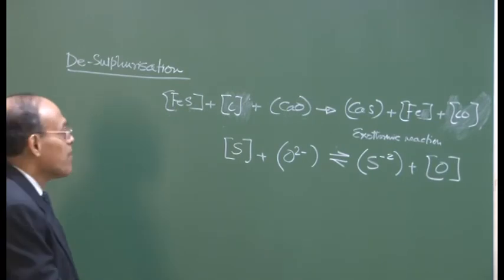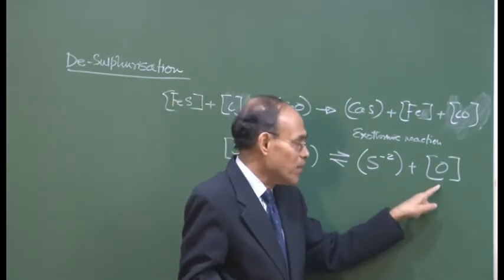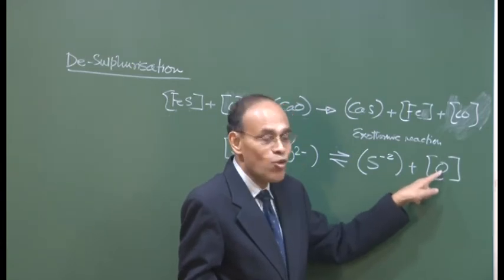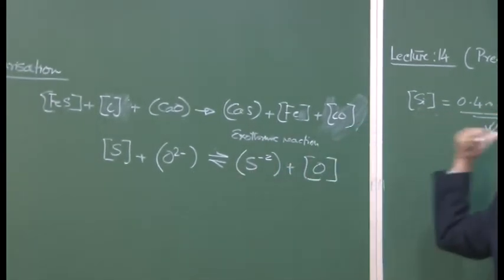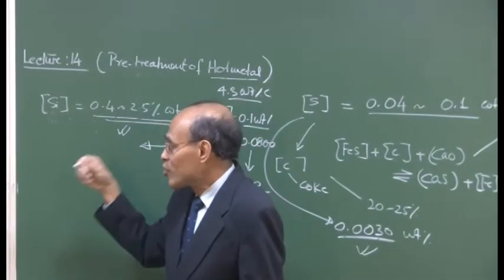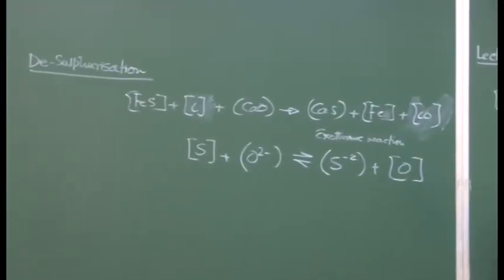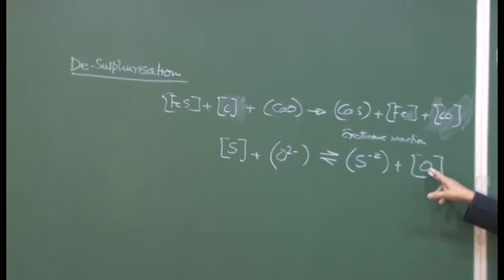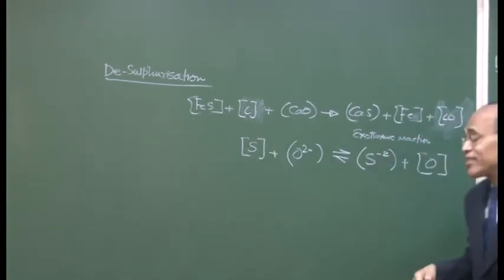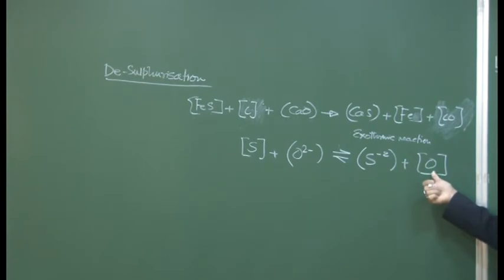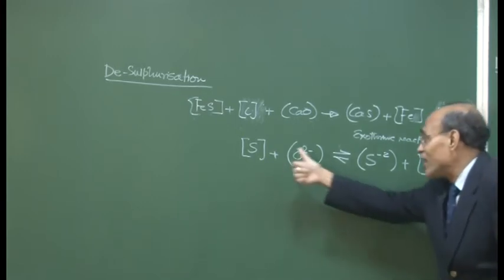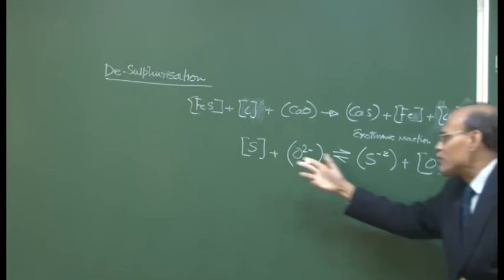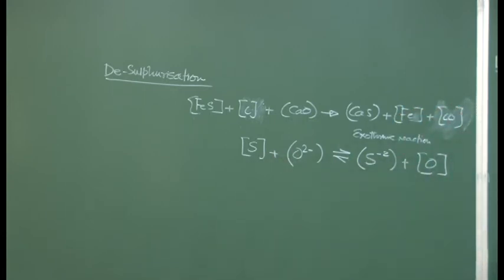In steelmaking, because I have carbon dissolved in the metal, that carbon will eliminate this oxygen. If the product is being continuously removed, the reaction will be facilitated in the forward direction. On the other hand, if there is no agent to remove oxygen, then oxygen concentration will increase, and that will force this reaction in the reverse direction. That is why I say a higher oxygen potential will not facilitate sulfur transfer from metal to slag. If there is a reducing environment, if you can take the oxygen out, there will be a significant transfer of sulfur from the metal phase to the slag phase.